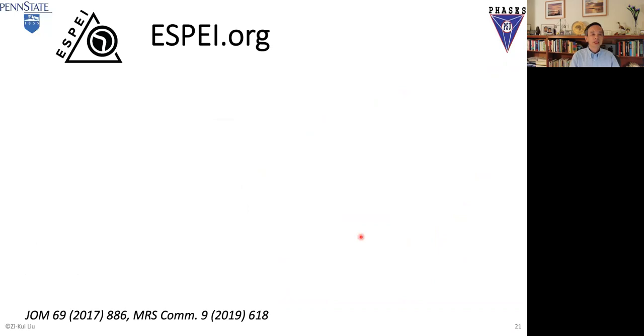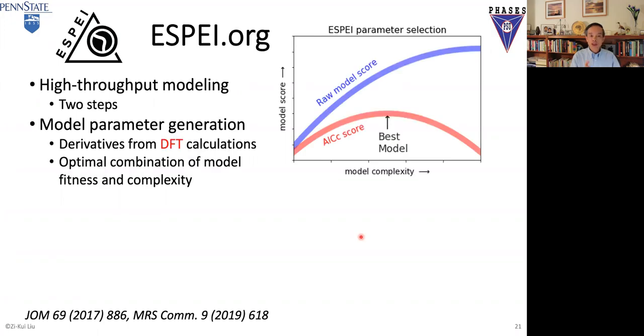Okay. Now you got all the data, right? So we want to speed up the development of the database and also use machine learning. Okay, so we developed a code called ESPEI. It's high throughput modeling. Basically, evaluate the model parameters. We're doing 2 steps. The first step is to use the derivatives only, the free energy derivatives. As I mentioned before, the derivatives in principle can get a complete database, right, with all the parameters in the free energy function, basically do integration.